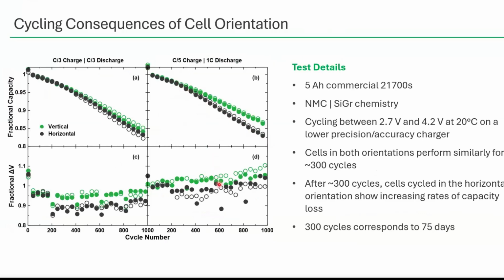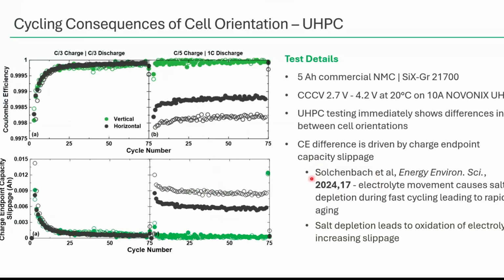There's been some interesting work done by a group associated with BMW that identified this as electrolyte movement caused by pumping, which causes really huge concentration gradients in the salt and salt depletion during fast cycling. If we picture a cell vertically, we've got this nice, almost capillary action of electrolyte getting back into the jelly roll as the cell rests - especially as we go to a faster discharge and don't give as much time for the electrolyte, which has been pumped out during charge, to come back in.